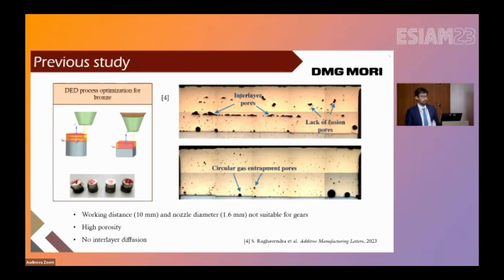The first one is that we discovered a posteriori that, for the sake of simplicity, DMG Mori decided to use a very small nozzle diameter with a very small working distance, with the result that the deposition rate is very small, so not compatible with fabrication processes, and the working distance is too short, so it's not able to deposit the bronze layer on the complex geometry constituted by the teeth of the worm gear. In addition, we detected porosity, and this can be detrimental for the structural integrity of the deposit, of the coating. And you see here that the interface between the steel and the bronze layer is very sharp. So this might be detrimental, leading to possible delamination of the bronze coating from the substrate.